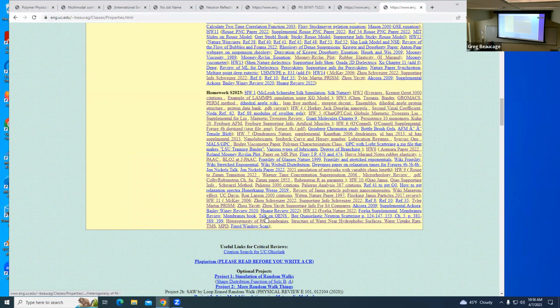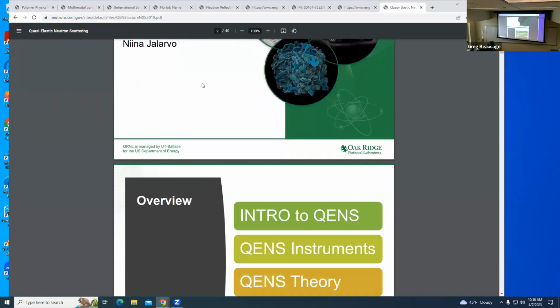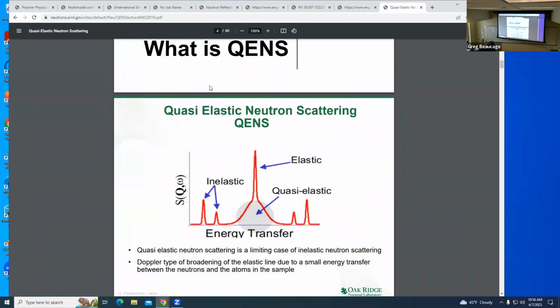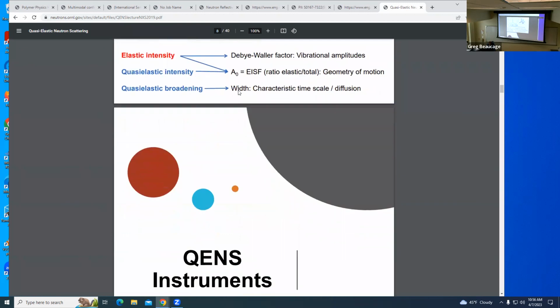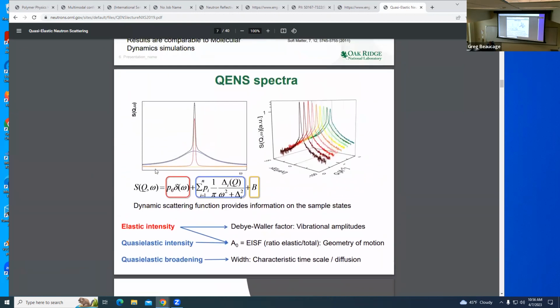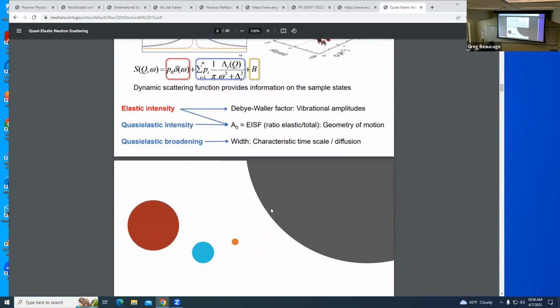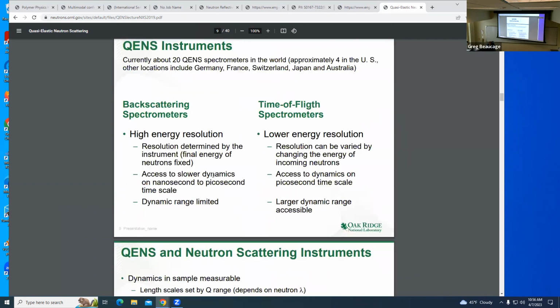That's that B book. There's that membrane book that I was talking about before. There's a talk here from Oak Ridge on quasi-elastic neutron scattering, which might be of some help to flip through if you want. Like here he shows there's a background. So you do the measurement, it looks like that. There's an incoherent background, there's an elastic peak. This is against energy or frequency at the bottom. And there's this Lorentzian at the bottom of it, which is kind of the dynamic stuff. And then he gets this delta omega and the other thing.